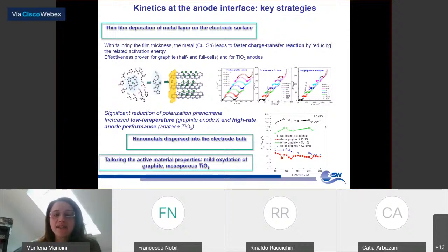some metal layers, especially copper and tin, which gave faster charge transfer reaction, which then translated to increased low temperature capacity, and in the case of anatase titanium dioxide, very high rate performance. Another approach was to use nanometals dispersed into the electrode bulk, and this was also part of the thesis of Mario Marinaro. And there was already attention to tailoring the active material properties. In the case of graphite, we performed mild oxidation, and in the case of titanium dioxide, thanks to the collaboration with the University of Ulm, the tailoring of the pores to a mesopore range.